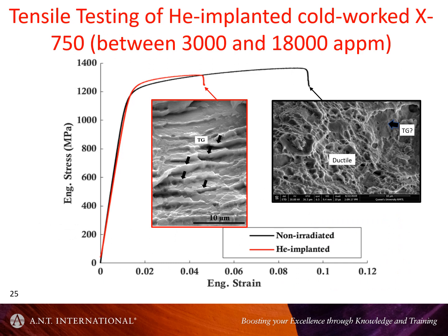So again, we look at Pouyan's work. And more recently, he did two pieces of work. One was on some bar stock material, and then the other was material that was fabricated to replicate the fabrication history of Inconel spacers. So a little bit more cold work, different kinds of heat treatments. And then Pouyan did the helium implantation and did the testing.